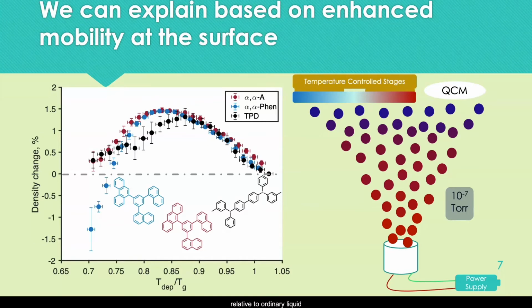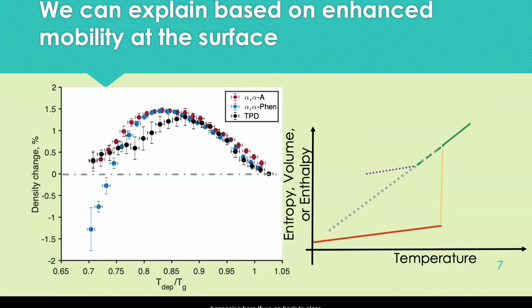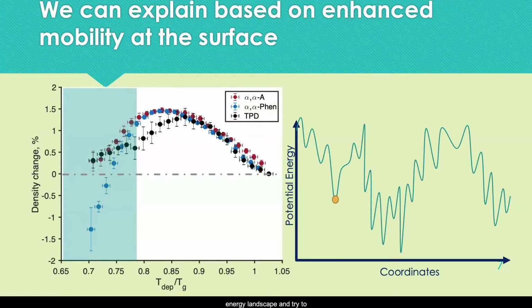And what's happening here, if we go back to our glass graph, is if we think about the high temperature, we have that enhanced mobility that I mentioned because we're at a high temperature, so the system is fast. But we're already fairly close to the supercooled liquid line. There's not really a strong driving force out of the state that it's in into a deeper, lower energy state. If I move to a colder temperature, I have that thermodynamic driving force. But if I look at the potential energy landscape and try to sample it, the system is going to be very slow to move through these configurations.